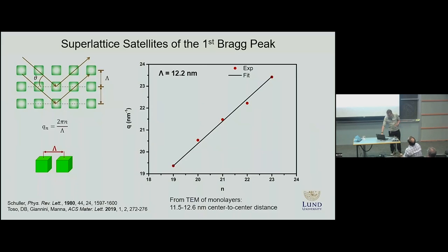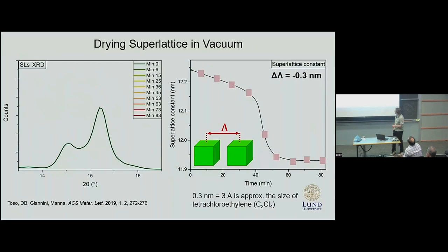So immediately, this diagnostic was useful for something like studying how superlattices dry under vacuum. Because right after self-assembly, which is done under ambient pressure, the film of superlattices is still wet. It's kind of like a wet bread, if you will.